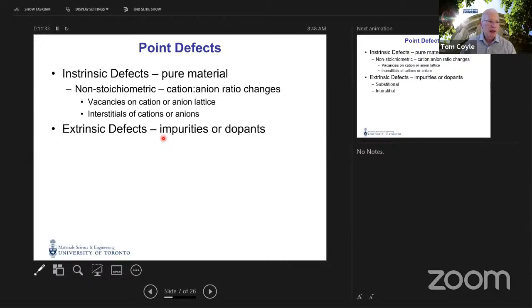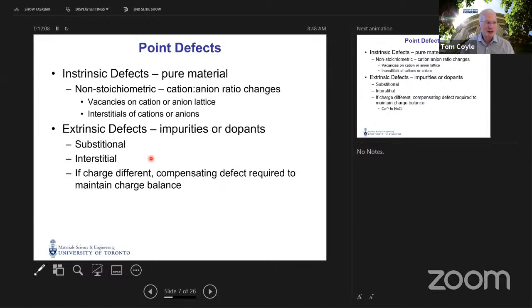And to round things out, extrinsic defects are associated with the presence of impurities or dopants. And like intrinsic defects, extrinsic defects can be either substitutional, replacing the atom that ought to be on a particular site, or interstitial, where these impurities or dopants exist at a position which is not normally occupied. And just to make things interesting, if this substitutional impurity or dopant has a different charge than the ion which it is replacing, we need to maintain charge balance. And so we need to create some sort of compensating defect in order to maintain charge balance.